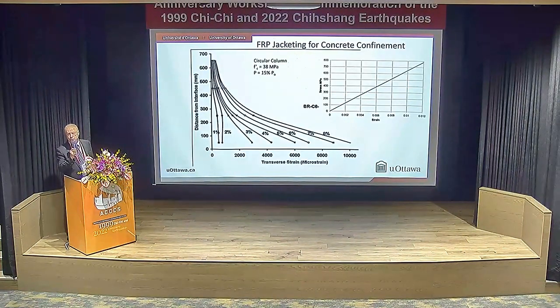In this case, we used CFRP carbon fibers with roughly 0.9 millimeter thickness for each ply, for each layer. Now, what is of significance, and this was a major contribution in our standard, was how much of the FRP strength one should use in design. Because our FRP went up to 700 MPa strength, but can we utilize all of that? Because typically FRP jackets have lower modulus, and will it have the ability to expand and confine or improve shear capacity of the column?